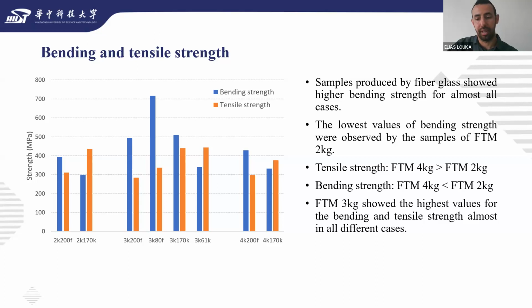Now, comparing the different materials by their samples, the lowest values of bending strength were observed for the samples of fiber mass of 2 kilo. It can also be seen that fiber mass of 4 kilo had higher tensile strength, but lower bending strength compared to fiber mass of 2 kilo. Samples with fiber total mass 3 kilo show the highest value for the bending and tensile strength in almost all different cases.